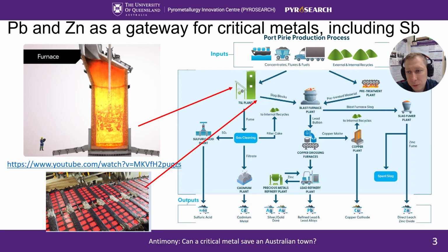Metallic lead, also called lead bullion, accumulates impurities, many of which are valuable but still need to be removed. The Drossing furnace removes copper in the form of molten matte, which is a sulfide liquid forming a separate layer floating on top of lead bullion. Copper matte is skimmed and then processed into a marketable product. After copper drossing, lead still contains most of the gold and silver, which can be separated using the process invented by Alexander Parkes in England in 1850. Also, the blast furnace slag can be further reduced with the production of zinc fume, shipped to Hobart and turned into a marketable product there.